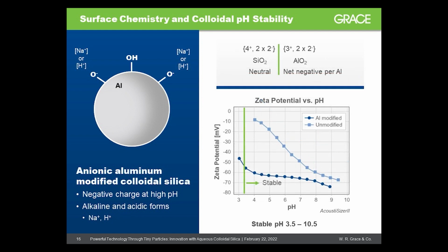An interesting modification of colloidal silica involves isomorphic substitution of aluminum for silica in the network under high pH conditions, where the aluminum is in tetrahedral form, like the silicon. This substitution has an interesting impact on the particle charge. Since aluminum is trivalent and silicon is tetravalent, isomorphic substitution of aluminum into the tetrahedral silicon network creates a charge imbalance of one negative charge per aluminum atom.